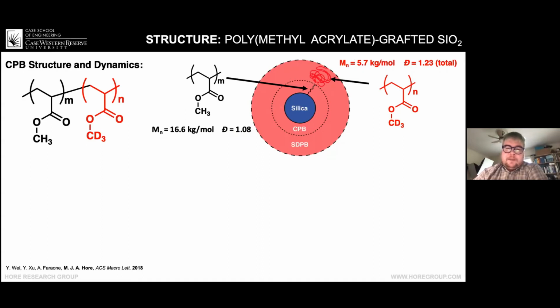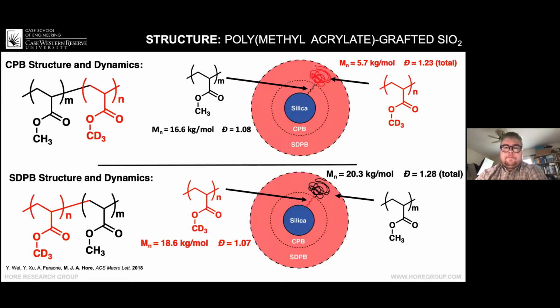Now, one thing that people ask me, especially when they see the next sample, is why is this molecular weight so low? Well, it turns out that, first of all, this monomer is very expensive. It's about $3,000 US per gram. So we didn't want to use too much of it. Also, there's no scattering from this region out here. So we're not getting anything out of it.